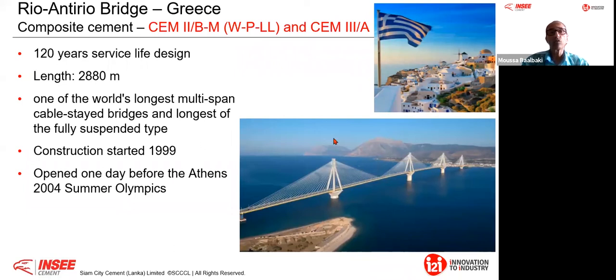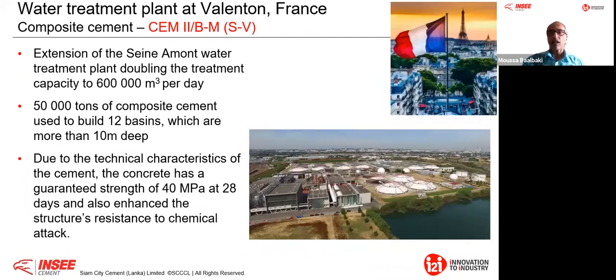Therefore, you see, that is what I want to say here, that we have proven technology. We have really a great experience for more than, let's say, 2-3 decades, where we have been using this type of cement successfully in Europe. This is why they are in the standard anyway. A last example where the system used composite cement with slag and fly ash is a water treatment plant in France. It treats around 600,000 cubic meters a day. Therefore, 50,000 tons of composite cement has been used to build 12 basins, where the depth is like a big swimming pool, 10 meters deep.